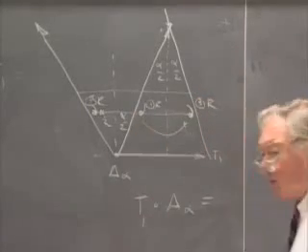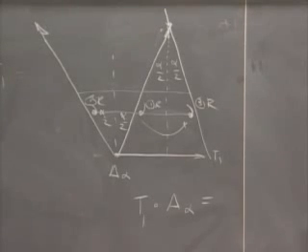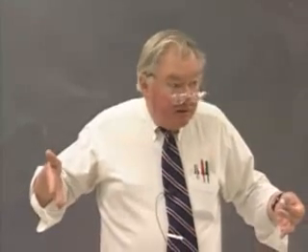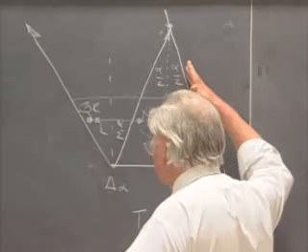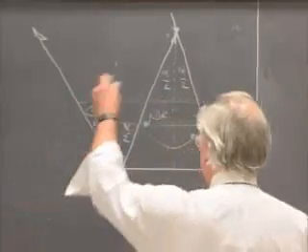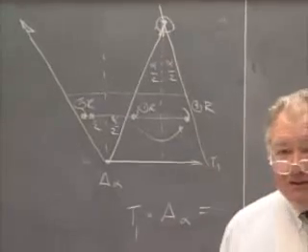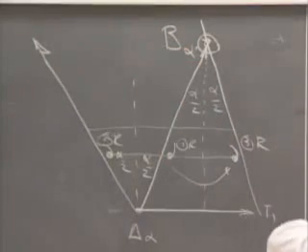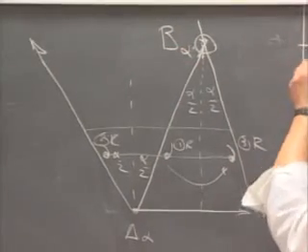And we next ask, what point is the point about which the rotation occurs? Then we used what at the time seemed like a trivial observation, that a rotation axis in space, or a rotation point in 2 dimensions, is the locus that is left unmoved by the rotation. So if rotating from here and translating over to here is equivalent to a rotation, and if the locus of the rotation has to be the point that's left unmoved, bingo, that's where the rotation occurs. And it's through the same angle, so we can label this an operation B alpha, and we know exactly where that point is going to be.